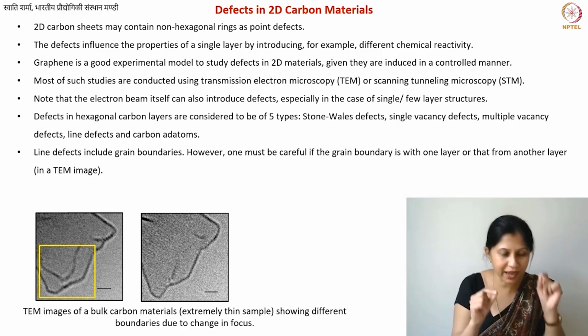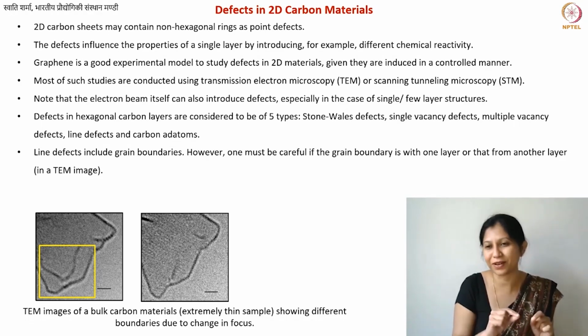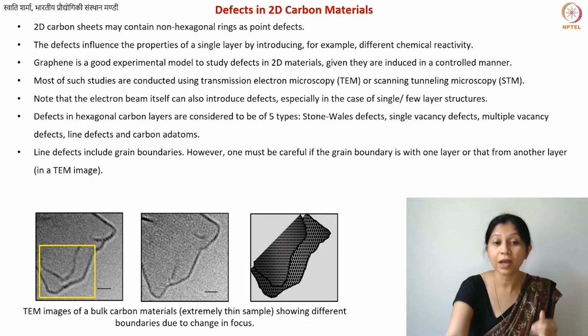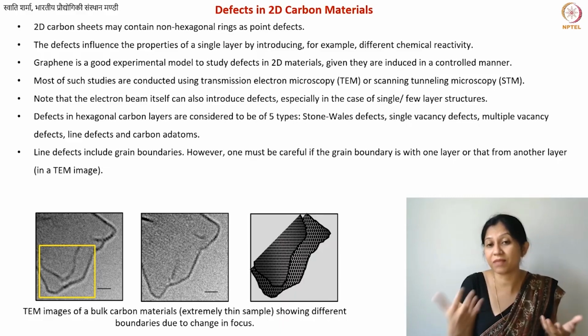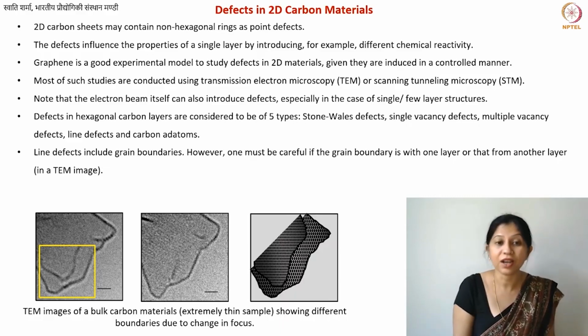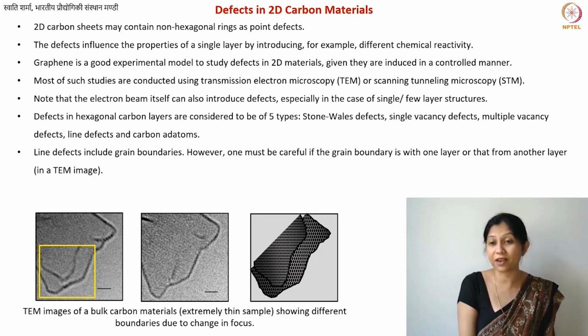And this is just by playing with the focus of your imaging. So this can also happen. There is a high probability that you have something like this. The structure actually is not even just one layer, there are 2 layers of graphene. Okay, so you need to be very careful when you are performing TEM imaging,